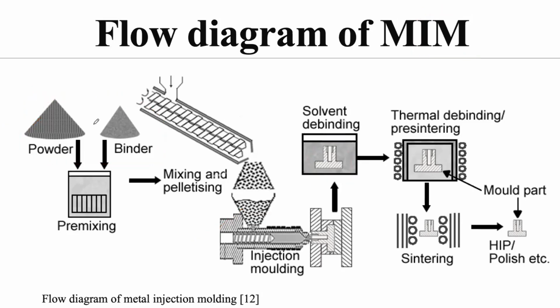But they need not go in one single step. Let's say I have made this particular part, where all the plastic material has taken a shape and the powder material is sitting there. If I try to remove everything in one go, what will happen? My metal powder has not bonded yet. They have not formed any bonds. So if I put it into a solvent, or do some kind of post processing, the polymer will go away immediately, but because the metal powder has not fused together, the part will be distorted, or the part will collapse. This is the reason that we have to go step by step, and in those steps we remove a fraction of these additives at every step.